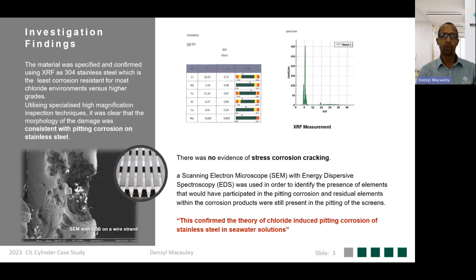The first thing we did was we analyzed the material using XRF, and it was confirmed that what we supplied was indeed 304 stainless steel. We then made use of some scanning techniques using SEM and EDS to check on the corroded wedge wire strand if there's any identification of what could have caused this excessive corrosion of stainless steel. And it was concluded that the presence of chlorides indicated that this is chloride-induced pitting corrosion, which we've never seen before in any of our other applications.